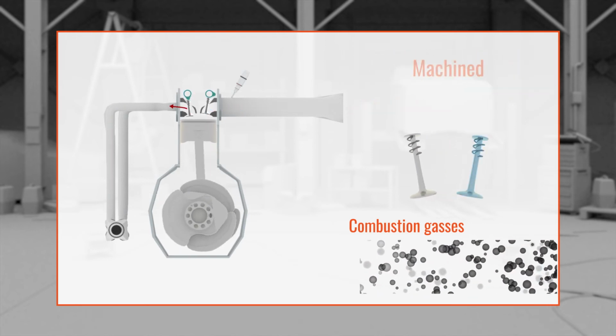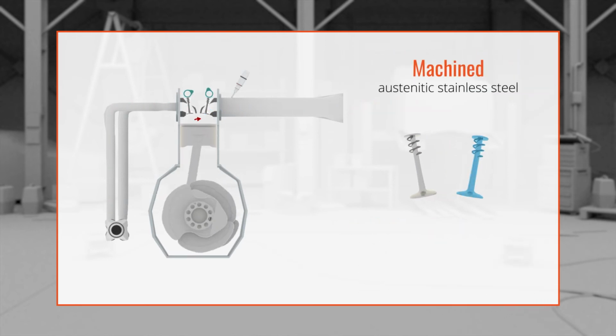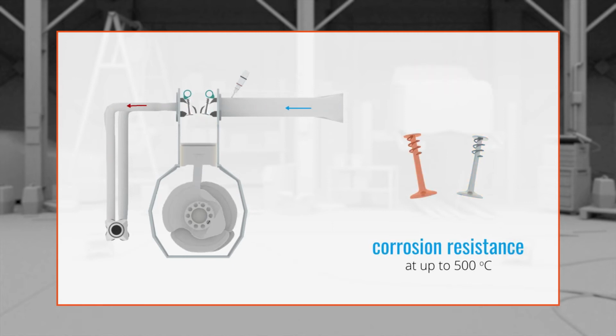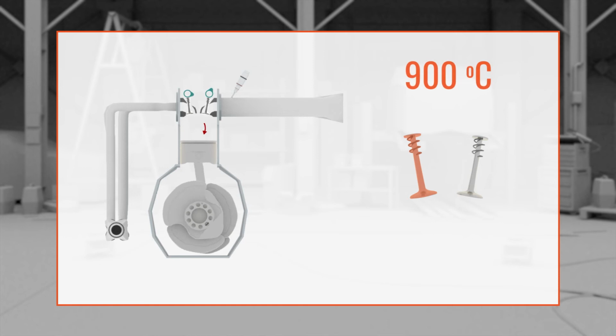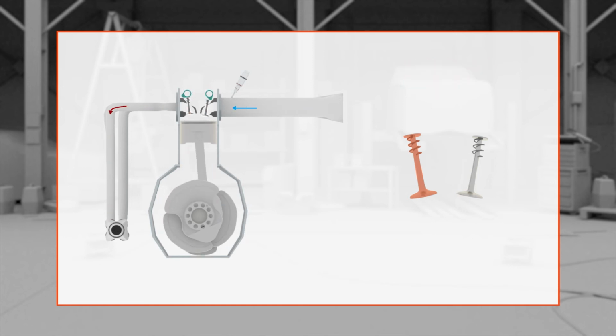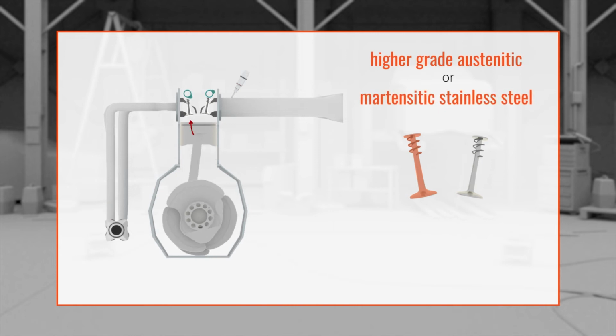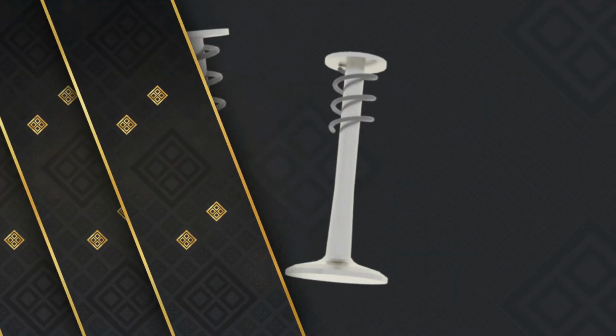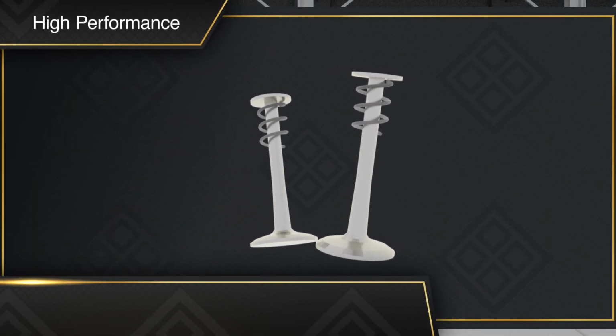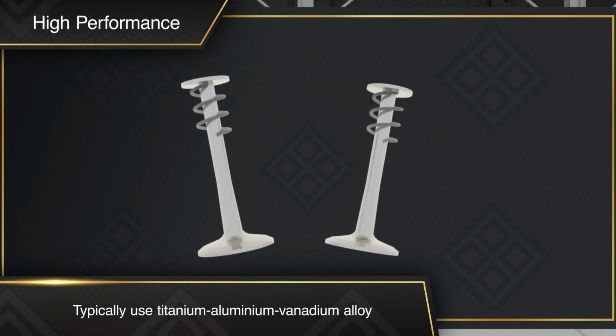Inlet valves are typically made from machined austenitic stainless steel for corrosion resistance at up to 500 degrees centigrade. Exhaust valves have to withstand even higher temperatures of up to 900 degrees centigrade, as well as higher pressures, and so typically use a higher grade austenitic or even martensitic stainless steel with nickel additions for heat resistance. High performance engines typically use valves made from titanium, aluminium, vanadium alloy.